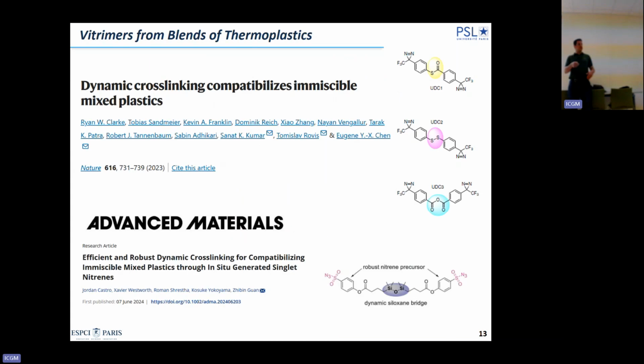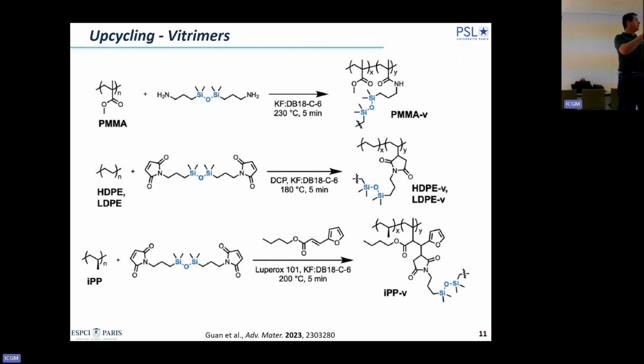And then here, one of the limitations, I would like to go back. One of the limitations is that you have to transform the polymer separately. And they are very well aware of this. They don't oversell. So the next step, which was done before, is can I develop a chemistry that I can use to functionalize at the same time, for example, HDPE, PP, PMMA, whatever I would like to recycle. And this is an important challenge in the field of mechanical recycling, but also in the field of polymer post-functionalization.